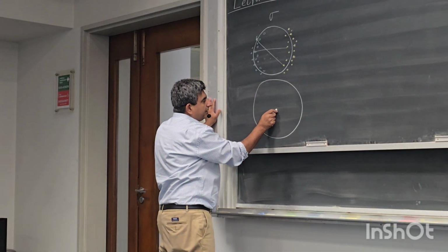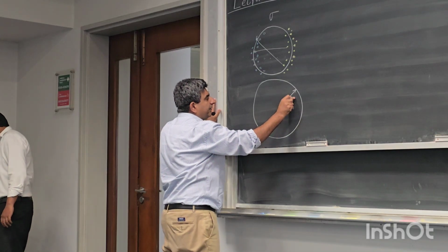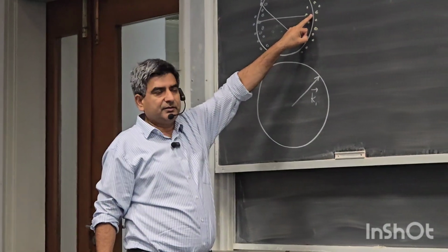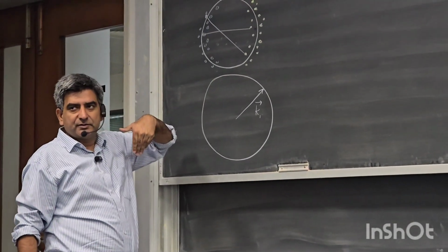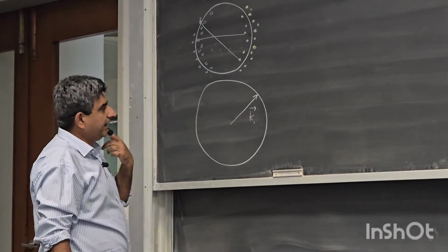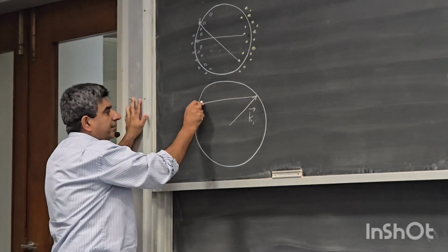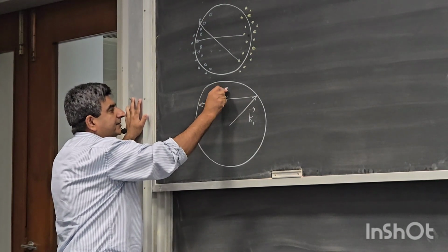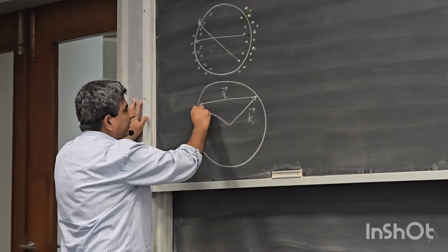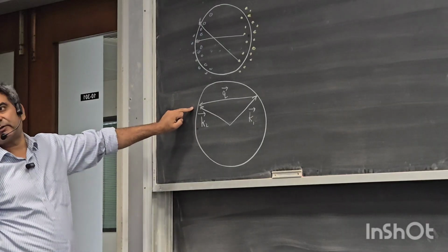So if this is an initial wave vector for an electron on the right side of the Fermi sphere, after absorption of a phonon whose wave vector is this long, one would obtain an electron with a wave vector k2 which is on the opposite side of the Fermi sphere.